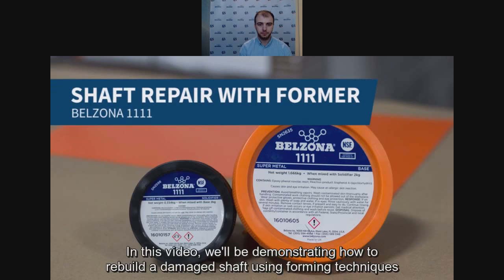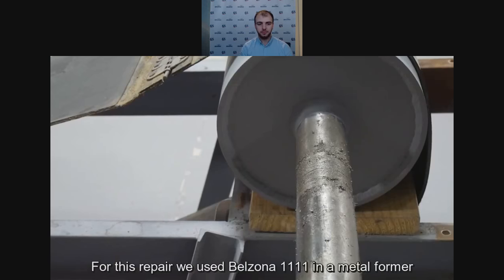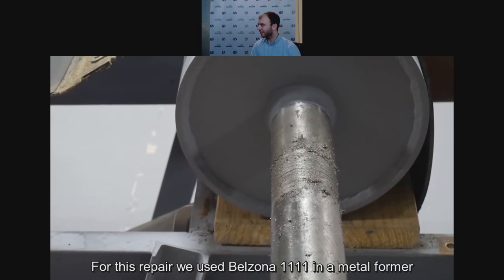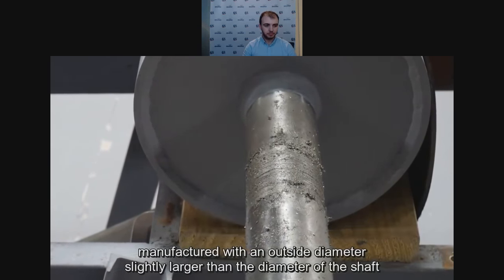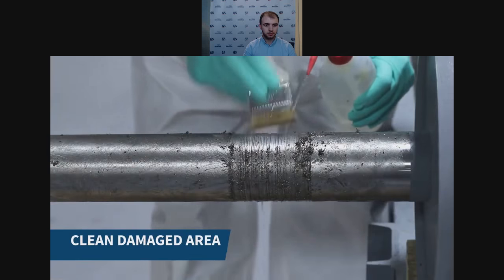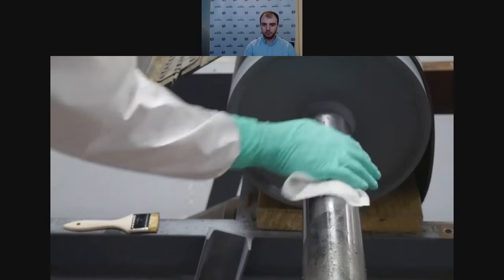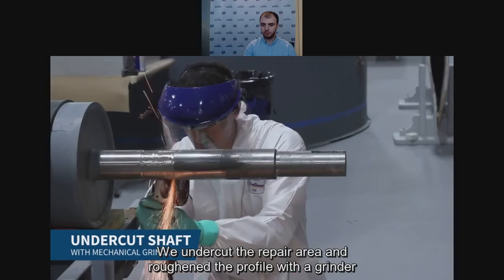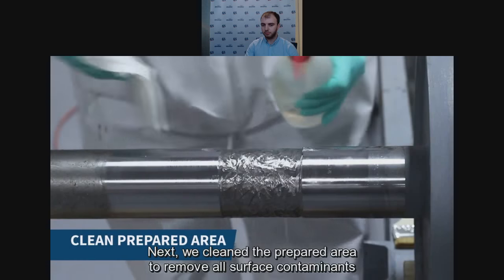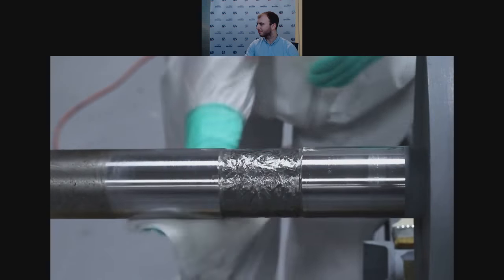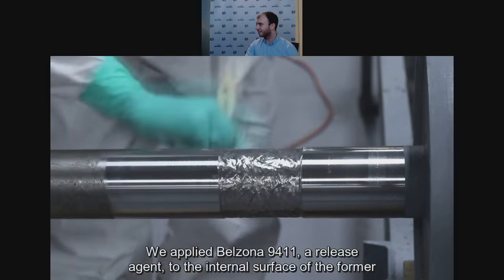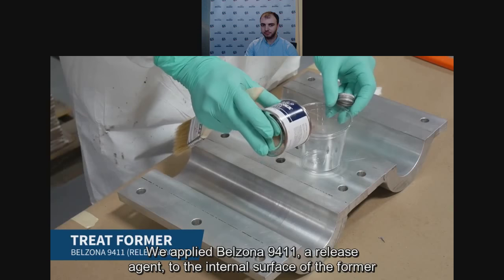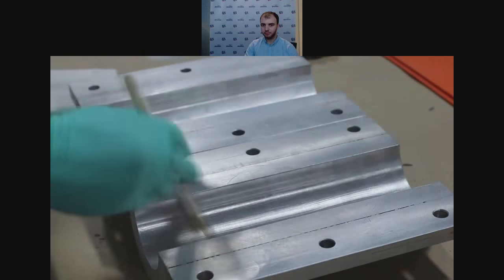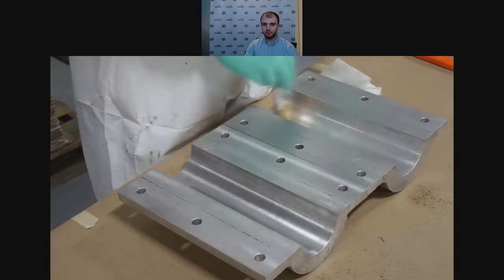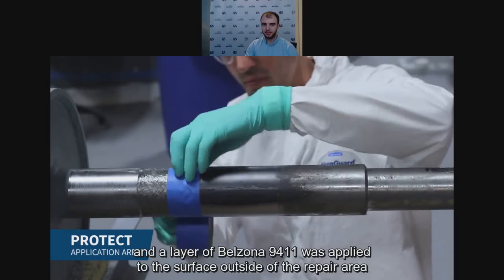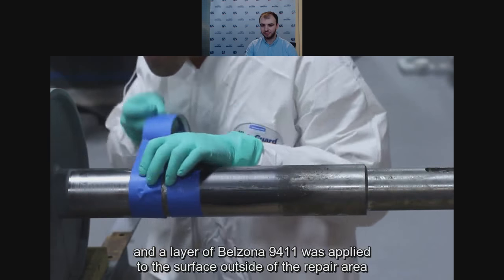In this video, we'll be demonstrating how to rebuild a damaged shaft using forming techniques. For this repair, we use Belzona 1111 in a metal former manufactured with an outside diameter slightly larger than the diameter of the shaft. First, we clean the damaged area of the shaft. We undercut the repair area and roughen the profile with a grinder. Next, we clean the prepared area to remove all surface contaminants. We applied Belzona 9411, a release agent, to the internal surface of the former. The repair area was then taped off and a layer of Belzona 9411 was applied to the surface outside of the repair area.